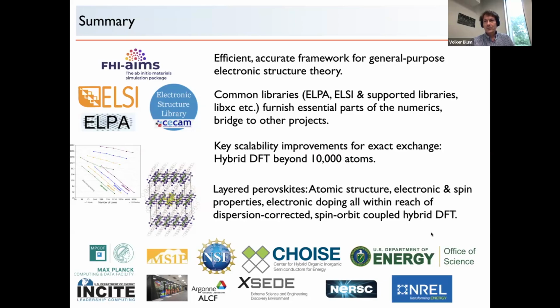Now in the energy band structures, we're calculating a different observable. We're calculating single particle-like energy levels and their energies. And in that case, the van der Waals correction could be included if we used a self-consistent van der Waals correction, but we use a non-self-consistent van der Waals correction in all of this, like practically everybody in the field does, because that appears to be good enough. So you calculate the energy self-consistently using the PBE or HSE functional, and then non-self-consistently you add the van der Waals. This means that the van der Waals correction in this application simply doesn't affect the energy levels.